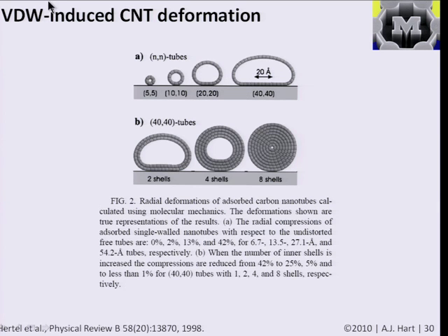The tube gets pulled down and really stuck to the surface and deformed, and this can affect its electrical characteristics and can also be important for how you might get it on the surface or get it off the surface. It means that this is a relatively strong force and interaction energy, so you can practically grip a nanotube just by having it sticking on a surface because of the strength of these interactions.